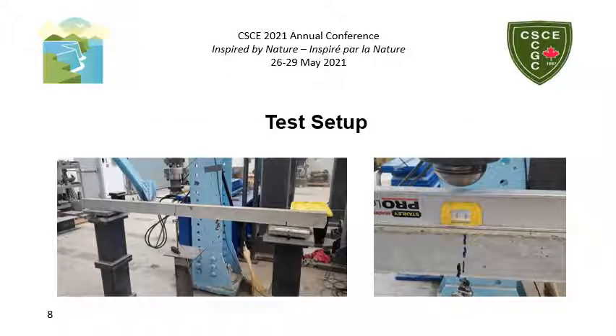A 3-point bending test setup with a pin roller configuration was used for all specimens. The load was applied through a load jack and pump. The distance from the supports to the point of application is 0.75 meter. Under the point of application, a 25 mm LVDT was placed to record the displacement. A load cell with 50 kN capacity was used to record the load in all tests.